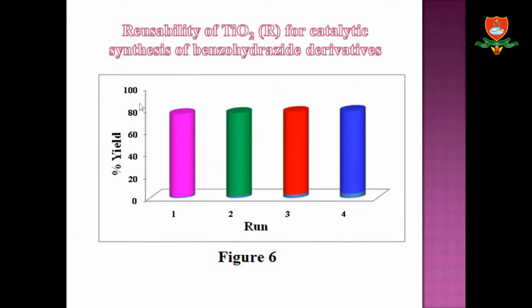This figure shows the reusability of titanium dioxide for catalytic synthesis of benzohydrazide derivatives. We reused this catalyst for the synthesis of compounds 1 to 4. During synthesis, we didn't observe any significant loss in the activity of the catalyst. Hence, this catalyst holds good for the synthesis of benzohydrazide derivatives.